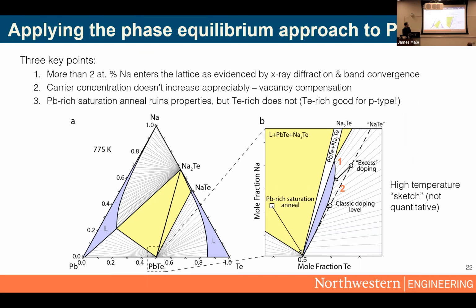We also see that the carrier concentration is not really enhanced despite that improved solubility, which suggests we have all these intrinsic defects pulling our single phase width away from that ideal doping line. And then finally, we can do lead-rich saturation anneals to find that we essentially have a 3-phase region of poor performance in lead-rich samples.